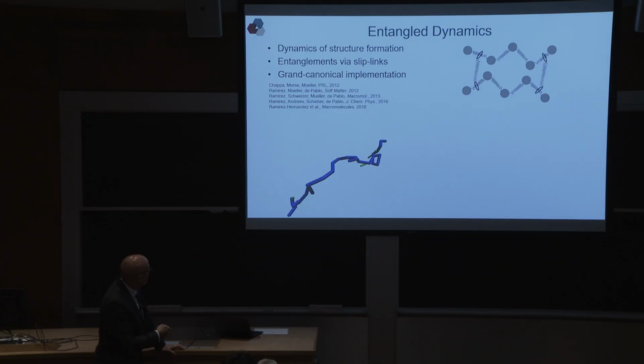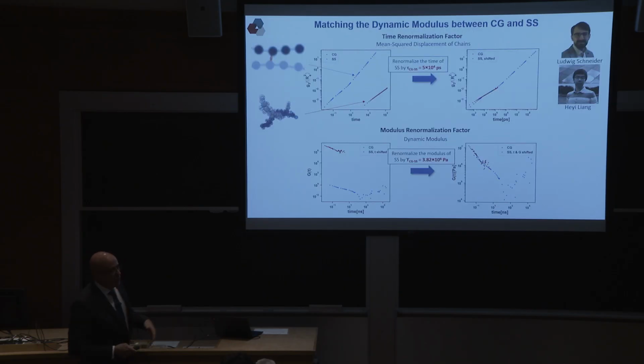What you saw in this movie over here were, okay, it's not playing, were slip springs along one molecule that are moving along, and when they get to the end, they disappear, and then at a time later, somebody shows up here and connects to a different molecule. All right. So once you have these models, you do the same thing again. You run the coarse-grained simulation that we had from before, and now the slip spring simulation that we have here, and you overlap them with each other, and you get a shift factor.